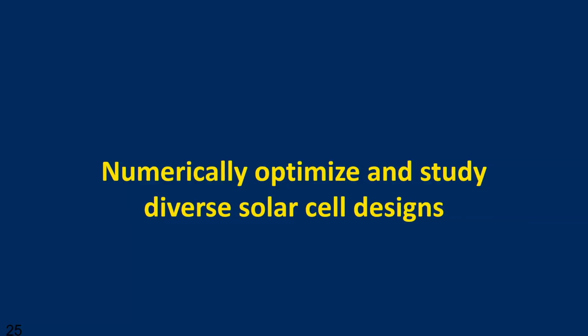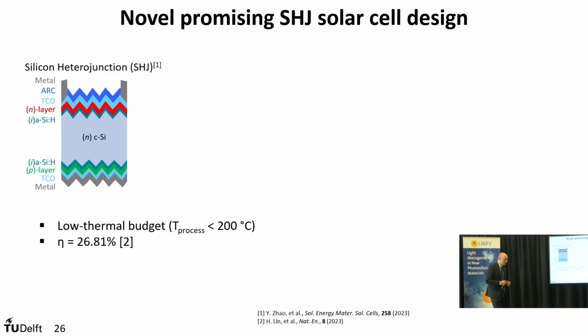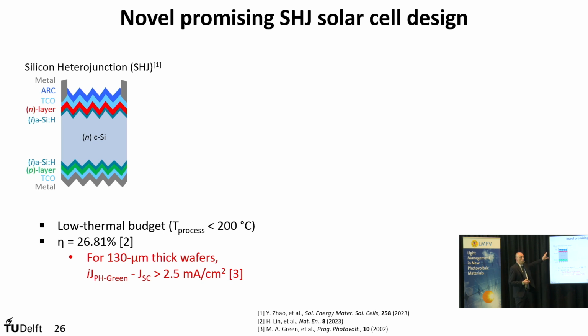Now, this brings me to the third part of my talk, to numerically optimize what is left to be optimized in terms of crystalline silicon technology. So I go back to this initial device, already state of the art, very difficult to beat. What is still missing here? For this type of device, 130 micron thick, we are still lagging behind by 2.5 milliamps per centimeter square with respect to the Green limit that would also be nice to exploit. And of course, it would be fantastic to have better light coupling. That means a higher current, higher VOC, higher fill factor.